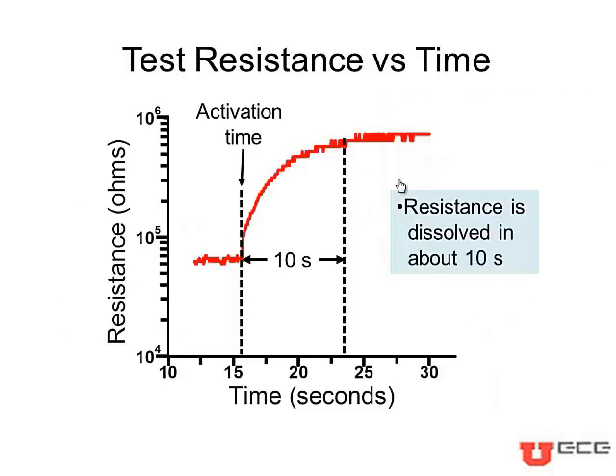This slide shows the plot of test resistance versus time when the device was activated. We can see that the test resistance rises from about 60 kilo ohm to a very high value in about 10 seconds, showing that the test resistor got etched by the released BHF.